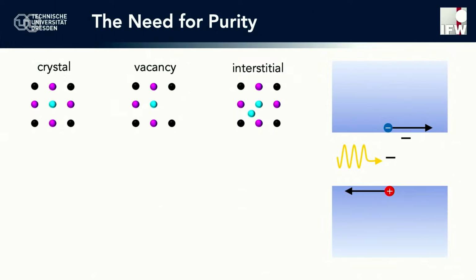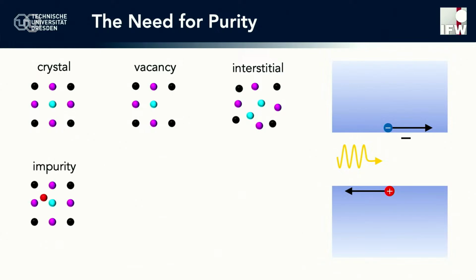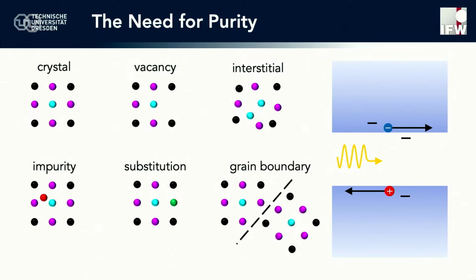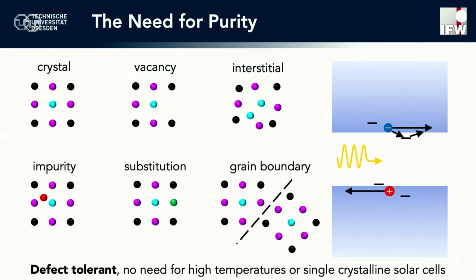But the crystal lattice of the perovskite is very soft and is able to actually change its configuration a little bit such that that defect is not formed. Other types of defects can actually lead to states in the bands and thus not affect the electronic structure at all. Same happens with grain boundaries, which lead only to the formation of very shallow defects. And that means that in this case, the solar cell would not really lose much performance because of the presence of defects. Such a material is then termed defect tolerant, and there's no need for high temperature processing.